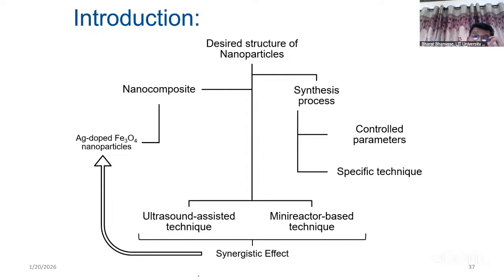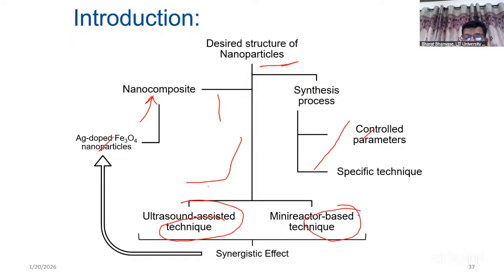In this case, we have to see the desired structure of nanoparticle, which is very important here, and the synthesis process that we need to consider. So Ag-doped Fe3O4 nanoparticle addition will create a composite, and that composite was prepared by ultrasound assisted technique and a minireactor - a very small reactor we used for preparation of nanoparticle, and its synergic effect was studied.